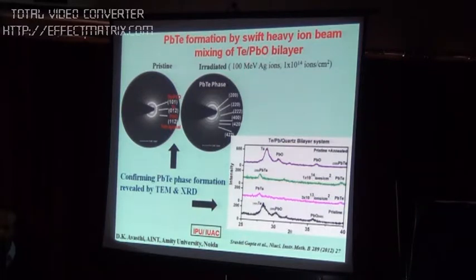So this is the pristine. You can see that you have tellurium and lead oxide. If you heat this system, then you get tellurium and lead oxide only. You don't get lead telluride. If you heat this tellurium and lead oxide film, then again lead oxide increases and tellurium remains tellurium. There is no mixing between the two.